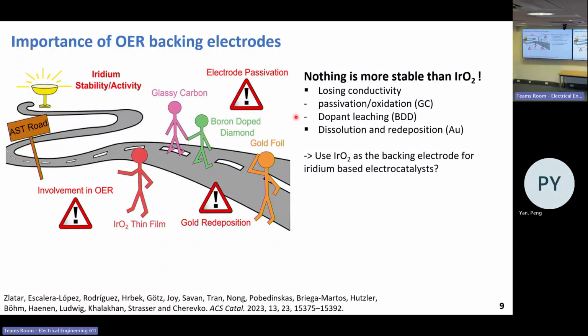And the problem of gold is that it can readily dissolve and redeposit onto iridium oxide, so it will block the active sites of iridium oxide and cause degradation.